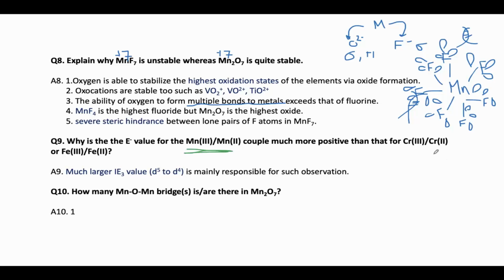But what happens in case of chromium 2+ to chromium 3+? Chromium 2+ is d4. If it goes to d3, then it will have a t2g3 configuration, which is quite stable. And in case of Fe2+ to Fe3+, Fe2+ is d6 and Fe3+ is d5. So it will also have the d5 configuration, which is also quite stable. So in the case of the manganese 2+ to manganese 3+ couple, the much larger third ionization enthalpy value, because it is the transformation from d5 to d4, is mainly the culprit behind this observation.